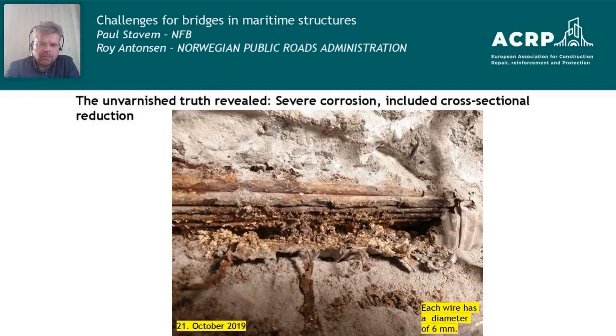And you can also see that the tendons here are partly enclosed by a very humid mass, and this mass here has been analyzed in laboratory, and it's a mixture of partially injected grouting, cementitious mass that has been frozen over the years, and very small particles. We only found small traces of chloride and sulfate inside here. But this void that you're looking into here, we have removed the duct here, right? So originally this happened inside of a closed duct, and there was humidity enough there to sustain corrosion, and air enough also.